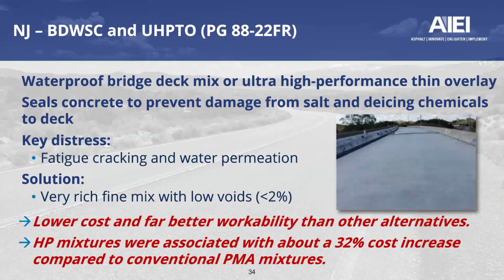Their primary usage is around bridge decks, but as well as bridge decks, they're also utilizing the highly modified materials on thin overlays in some key high performance areas. Their key distress that they are working to combat is fatigue cracking and also creating impermeability. As you might suspect with bridge decks, that's very important. They are utilizing a fine graded mix with low air voids.